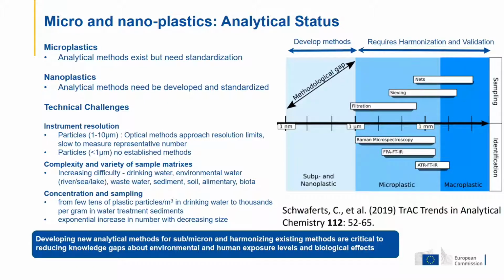The figure shown by Schwaferts, although published in 2019, is a fairly good illustration of the situation which still exists today. Basically, for the detection, identification and enumeration of microplastics, the optical diffraction limit remains the dominant factor in dividing the measurable from the non-measurable, with the barrier being around 1 micrometer.